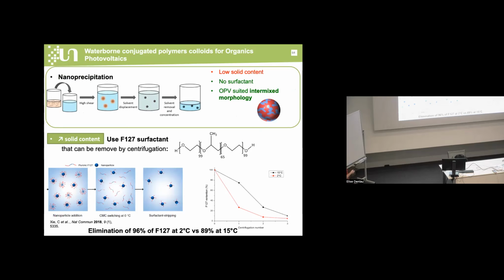F127 surfactant, which is a Pluronic with a thermoresponsive critical micelle concentration, so that you can remove this surfactant by using centrifugation at low temperature. So you can remove the excess of the surfactant.